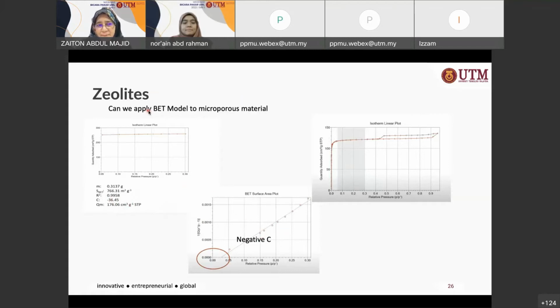So remember, zeolite is a microporous substance. When they ran the full plot, they noticed that it is a microporous substance, and this particular range is already the saturation limit. So that's why you do not get anything when you run points between 0.05 and 0.3. So you might want to run it at a lower pressure, or you might want to do a few other modifications in this case. The isotherm is already saturated in the classical BET range.